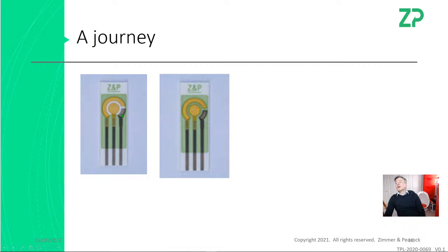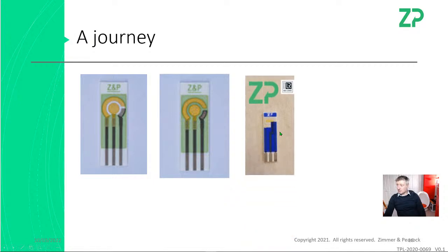The 101 has a white layer around here, and that's a little hydrophilic. So what tends to happen is things spread out a bit. So we put a hydrophobic barrier here, and that sometimes helps to contain the solution. That one we call the 101B, because there's a bit of a barrier layer there, and it helps to contain the drop. So that was a bit of an improvement. I said it was a bit of a journey. The electrode that we recommend today is this 303. It's smaller, it's half the price. You look at the rectangular design and say, what's that all about?